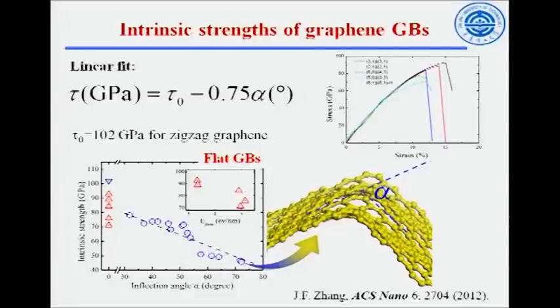More importantly, we check the intrinsic strength, which you can determine from the dropping point of the stress-strain curve. Then you can extrapolate this intrinsic strength, and you get it as a function of inflection angle. That's the plot we get. By extrapolating to zero, we can have a linear fit of this relation. This means that with inflection, due to the existence of grain boundaries, the intrinsic strength drops significantly, and it drops almost linearly. The tau zero is the upper limit, which is actually calculated for zigzag graphene, about 100. For those without inflection, there is still some trend, as we can see, since for zero inflection there are some symmetric grain boundaries.